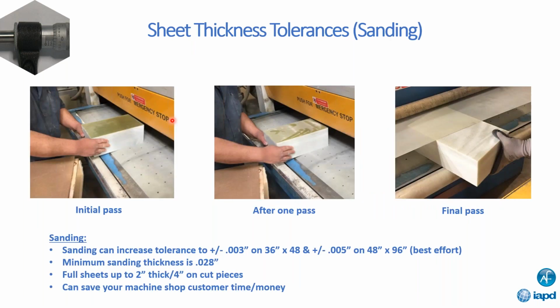One way to eliminate the wide tolerance range is through the sanding process. Our sanders can take a tolerance from plus or minus 12 thousandths and turn it down to plus or minus 3 thousandths, or plus or minus 5 thousandths on a full sheet that's a 48 by 96. You can see from this left to right picture, here's the initial pass. You notice the gloss is still intact. After one pass, you can see some of the gloss has been removed. And then on the right-hand side, after the final pass, all of the gloss has been removed. That particular piece is about 4 inches thick, but we can get that down to plus or minus 3 thousandths.